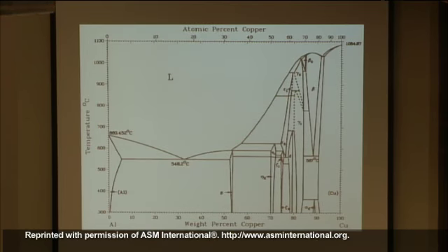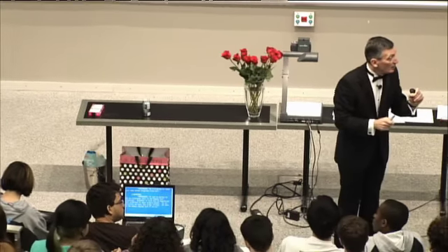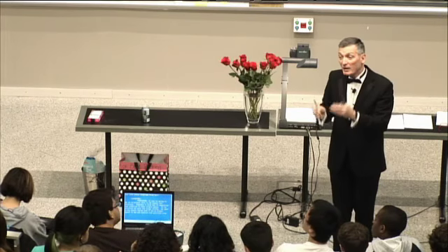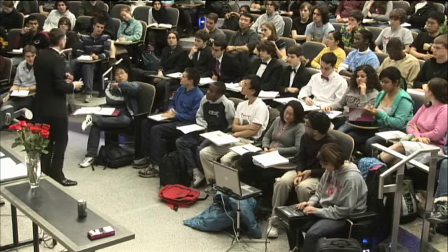All right. So I'm going to show you some phase diagrams from hell. You're going to be on airplanes. The airplane alloys, aluminum copper. It's about 4% copper in aluminum. Now remember, I just told you about 1% magnesium in aluminum to give you single phase. In the case of the airplane, we want to make the wings strong. So what we do is we come down into here, which is a two-phase regime, and if we're clever about it, we can control the particle size of that second phase. And by controlling the particle size, we can cause grain boundaries which can arrest the dislocations and make sure the wings don't fall off.